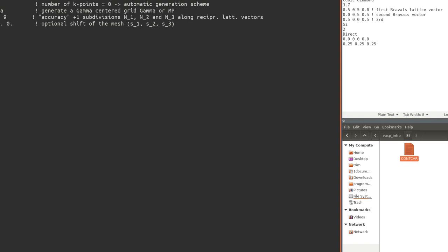So usually the charge distribution file can be calculated with low density, whereas density of states and band structure should be calculated with quite a high number of k-points. So if you had 20 k-points in the last step, I think that either 25 or 30 should be pretty enough.